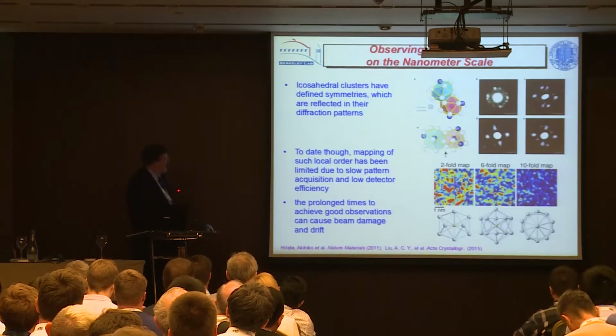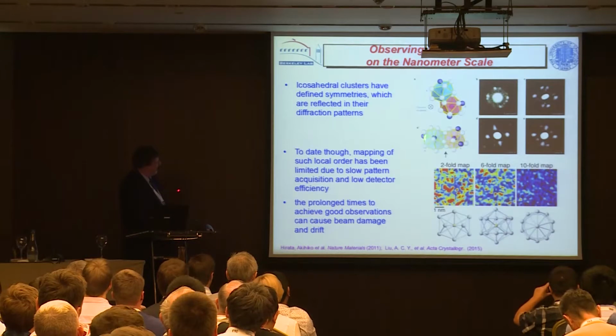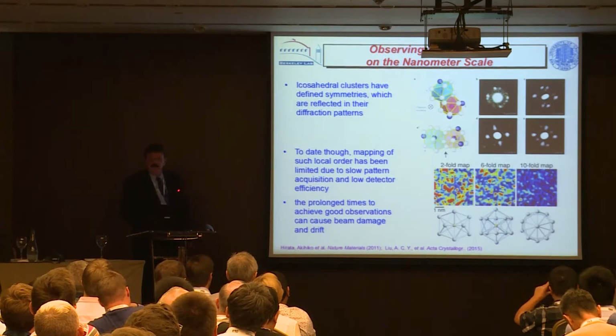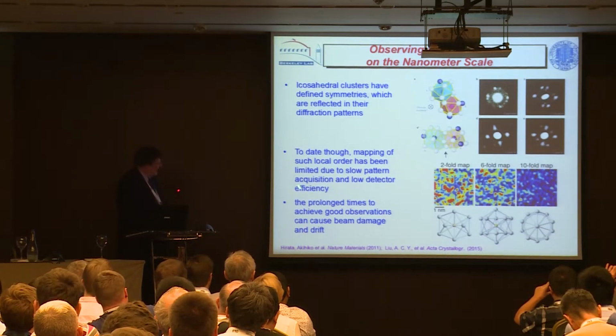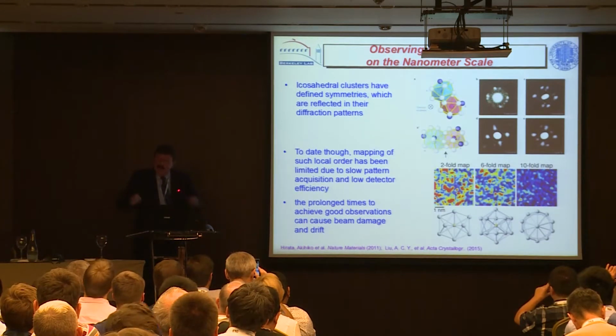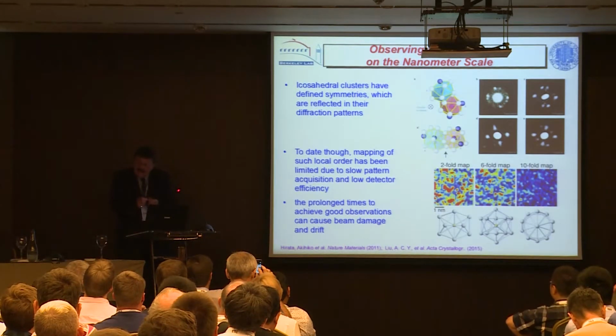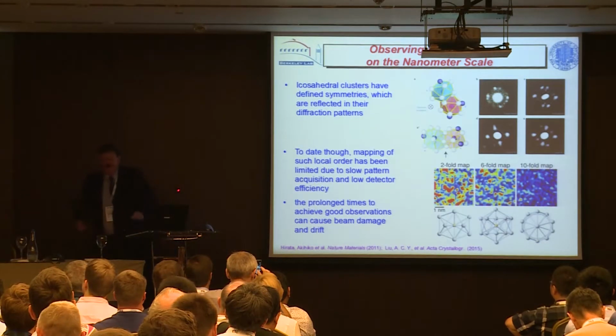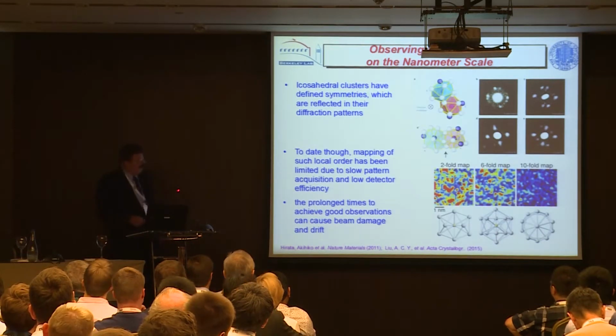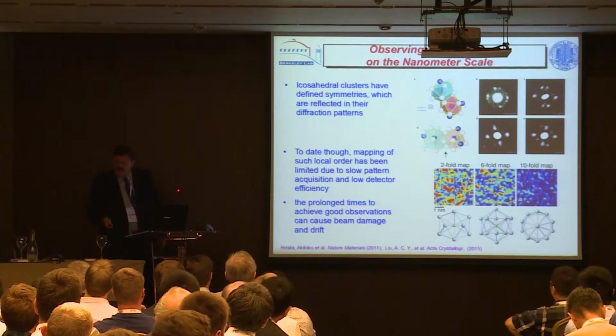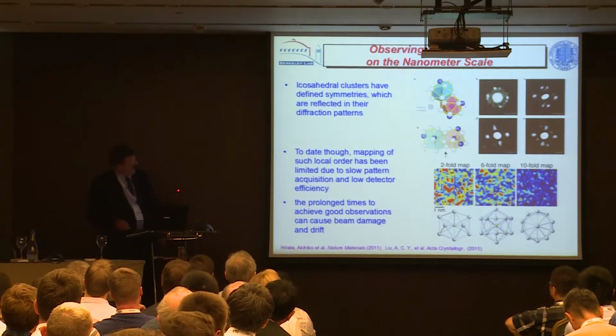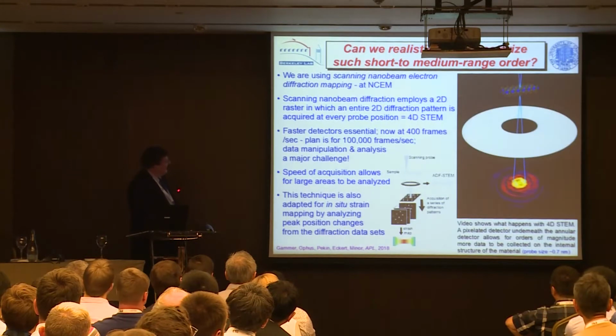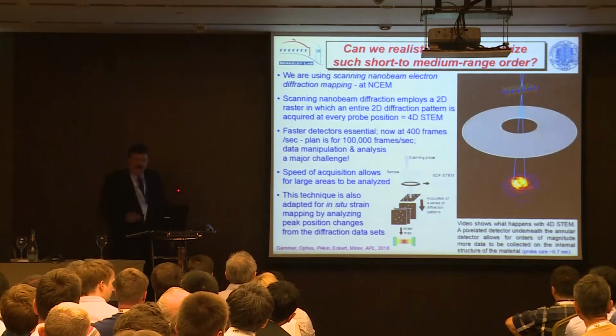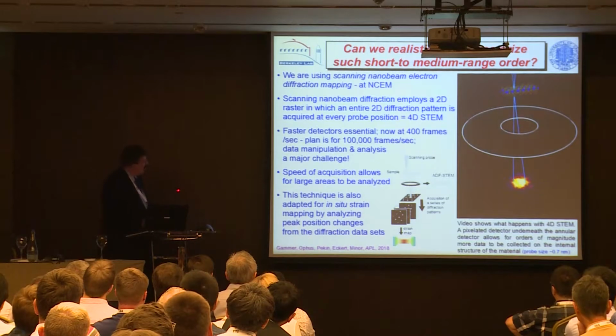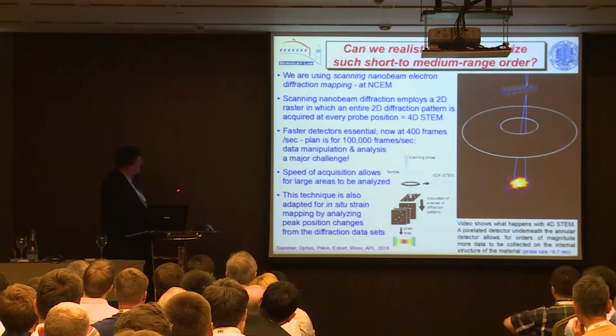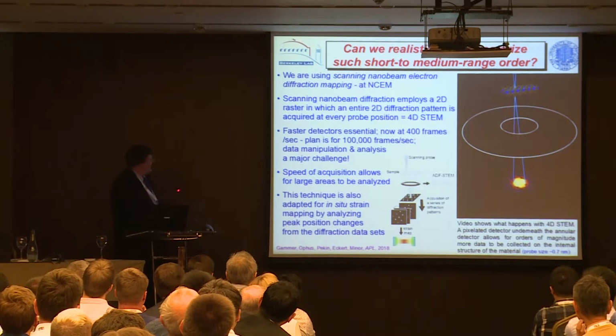So people have tried to do this. You can get diffraction patterns from these different local regions of symmetry. But if you try to map them across a large region, you're looking at a very small region with high resolution, but you want to map over a large region, there's problems. It takes too long. You tend to damage the foils. You can get drift. And so we've come up with a new technique. This is being done at the National Center for Electron Microscopy. I'm working with Andy Minor there. And we call this nanobeam scanning, nanobeam diffraction.